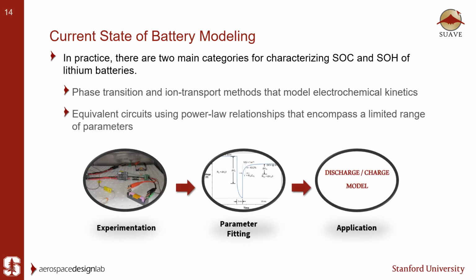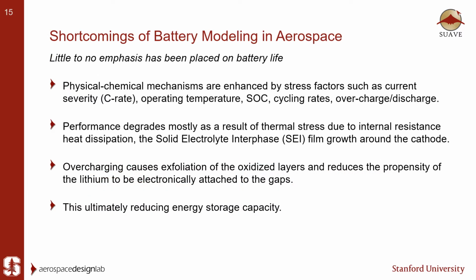The second method, equivalent circuit models, which use power law relationships that encompass a limited range of parameters which can be obtained from experimentation. As shown below, experimentalists typically run experiments using accelerated aging tests. Then they use tests such as the pulse polarization test to gather parameters for fitting, and then use discharge and charge models for a particular application. However, there are several shortcomings within the aerospace industry, as little to no emphasis has been placed on modeling battery life. There have been some studies that have modeled battery prediction or state of charge during a particular mission. However, little to no emphasis has been placed on modeling a battery throughout an entire mission over repeated use.